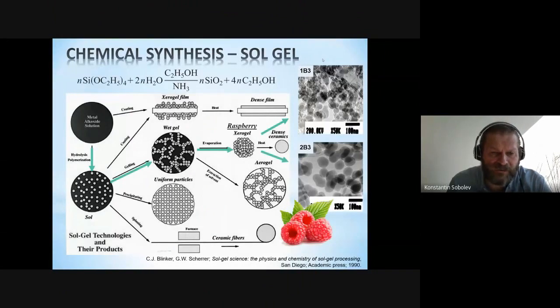When we speak about production of nanoparticles, where those are coming from, there are different methods to produce nanomaterials. I'm not going to cover all, but something we tried in the lab: we used the sol-gel method, which is a relatively easy method to realize in the lab. You use a precursor, usually TEOS, and an alcohol environment. You can produce it in acidic media, you can produce it in alkali media, and obviously the product you have is nanosilica and alcohol in solution.